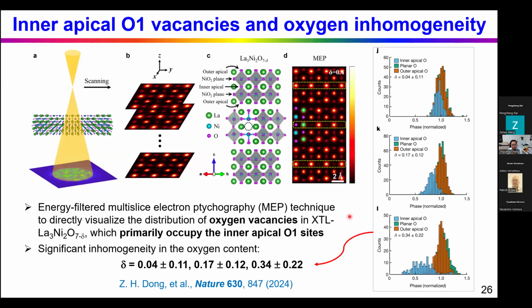Actually, according to this most recent paper published in Nature, one of my colleagues, Chen Zheng, developed the energy filtered multi-slice electron ptychography, this MEP technique. I'm not very familiar with this one, but we just mention this MEP technique. It's a very advanced STEM-like technique, so they can directly image the oxygen vacancy. By using this technique, they also measured the 327 crystal from Wang's group. They found that the oxygen vacancy is mainly located at the inner apical O1 site. So this O1 site.